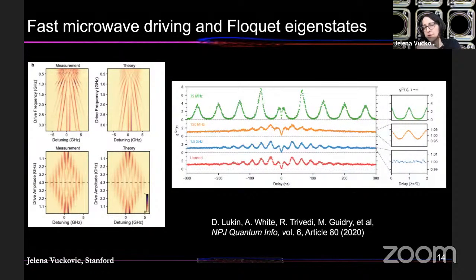So this is again on silicon carbide color centers, silicon vacancy in silicon carbide. When you apply periodic drive on a color center, you expect to see Floquet eigenstates in the system, and that's theoretically predicted, and we observe it in the measurement. So you have this kind of spectrum of eigenstates that are occurring, and they depend on the drive frequency. And we also show from our second-order photocorrelation measurements that we actually indeed work with single color centers in these experiments. They're modulated, and the signature of modulation appears in the side bands of your second-order correlations.